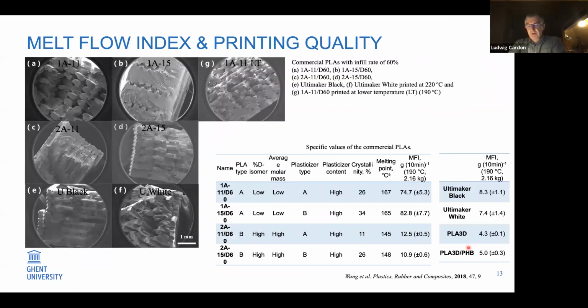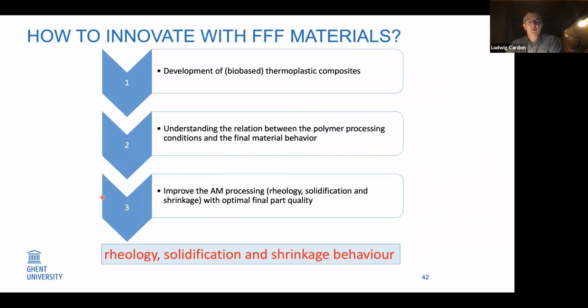So then finally afterwards, we investigate by some imaging the morphology structure of different kinds of materials. You see here, in this case, PLA material, where we use a percentage of the D isomers. Due to a patent, we can't mention the composition, which is the percent of D isomer in the PLA, which can be either low or high, and the average molecular mass is low or high, and then we combine that with a plasticizer A and B. So by playing around with our parameters and blending and the different kinds of melting points, we investigate, combined with the melt flow index or viscosity, the printing behavior, and finally the density and inter- and intralayer adhesion of materials. So that's, as an example, a part we investigate.